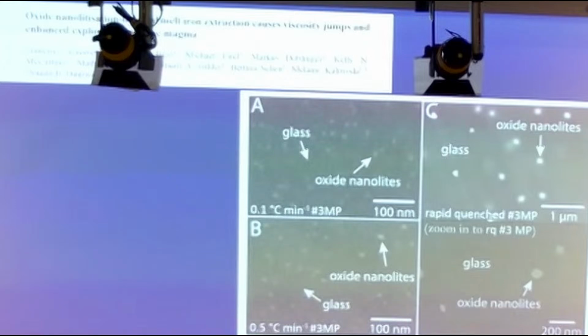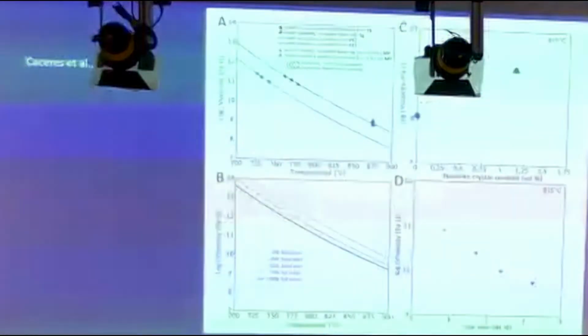And it's a separate set of viscosity measurements, so we made a separate paper out of it with separate co-authors, of course. And you see oxide nanolitization induced melt iron extraction, it's a lot of words to what we mean, causes viscosity jumps and enhanced, so he's bold enough to say, I think this was a geology paper, causes enhanced explosivity in silicic magma. Because if you can push your viscosity up, the propensity for explosions goes up with it.